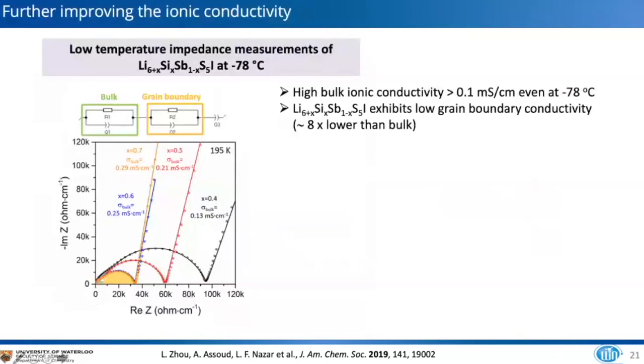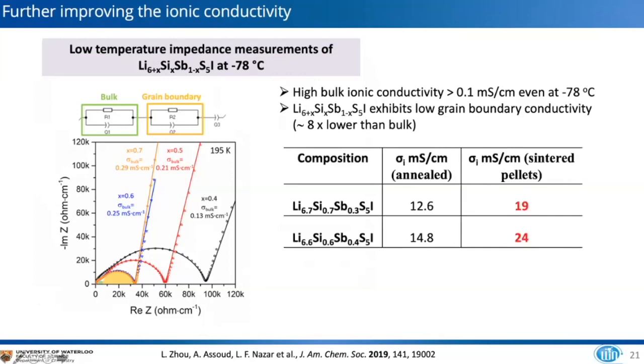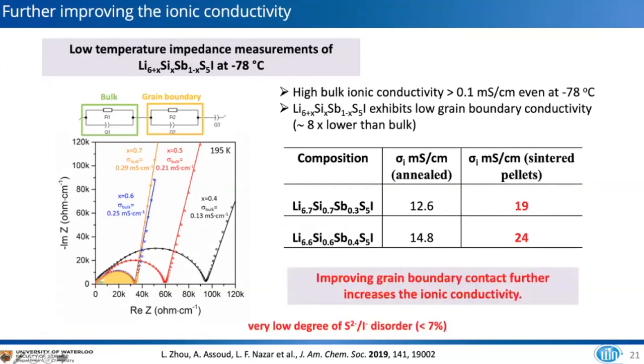And grain boundary effects are important. This just shows some impedance data where we can separate the bulk from the grain boundary. So in fact, there are considerable grain boundary effects. In other words, there's low conductivity, especially when we get to higher values of silicon. But at these conditions, by sintering the pellets, we can get conductivity upwards of 24 millisiemens per centimeter. So improving the grain boundary contact certainly increases the ionic conductivity, but the bulk is excellent. And this is achieved with a very low degree of anion disorder between the sulfide and the iodine.